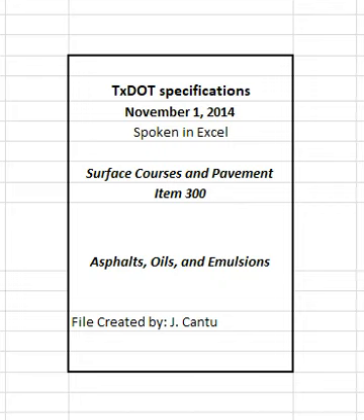3. With all pre-certification samples of CMS-1P or CMS-2P, submit certified test reports showing that the rejuvenating agent and latex meet the stated requirements. Submit samples of these raw materials if requested by the engineer. For preparation of latex films, use any substrate which produces a film of uniform cross-section. Apply latex using a drawdown tool that will deliver enough material to achieve desired residual thickness.